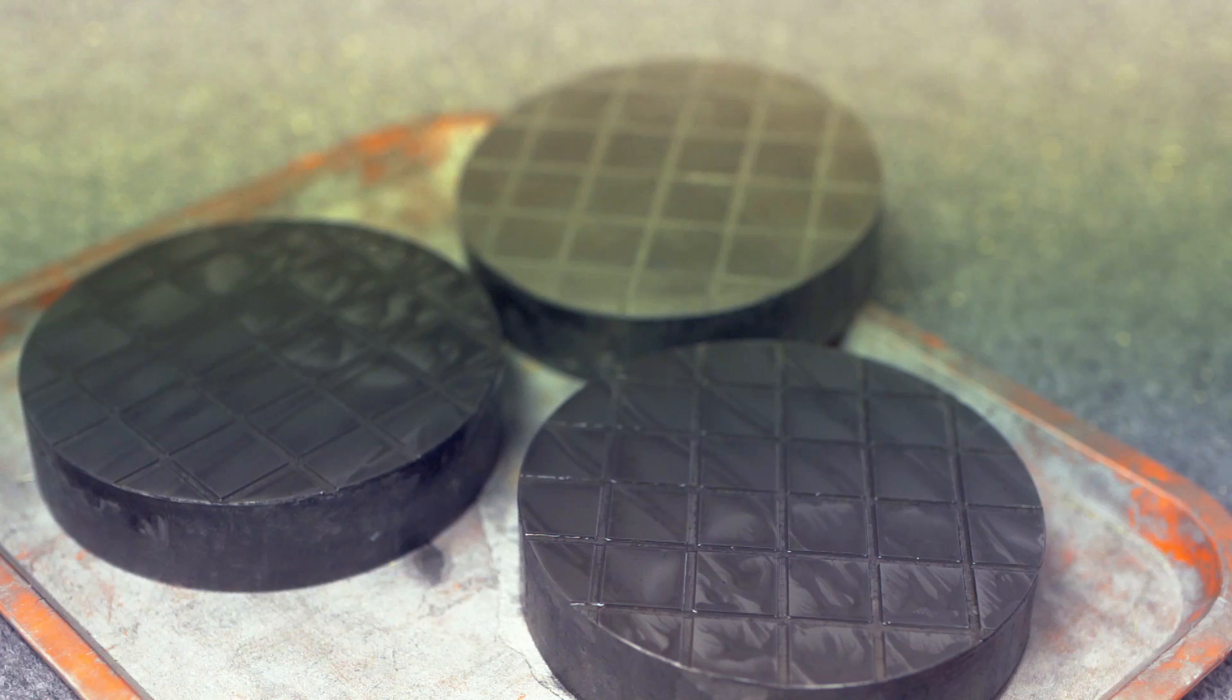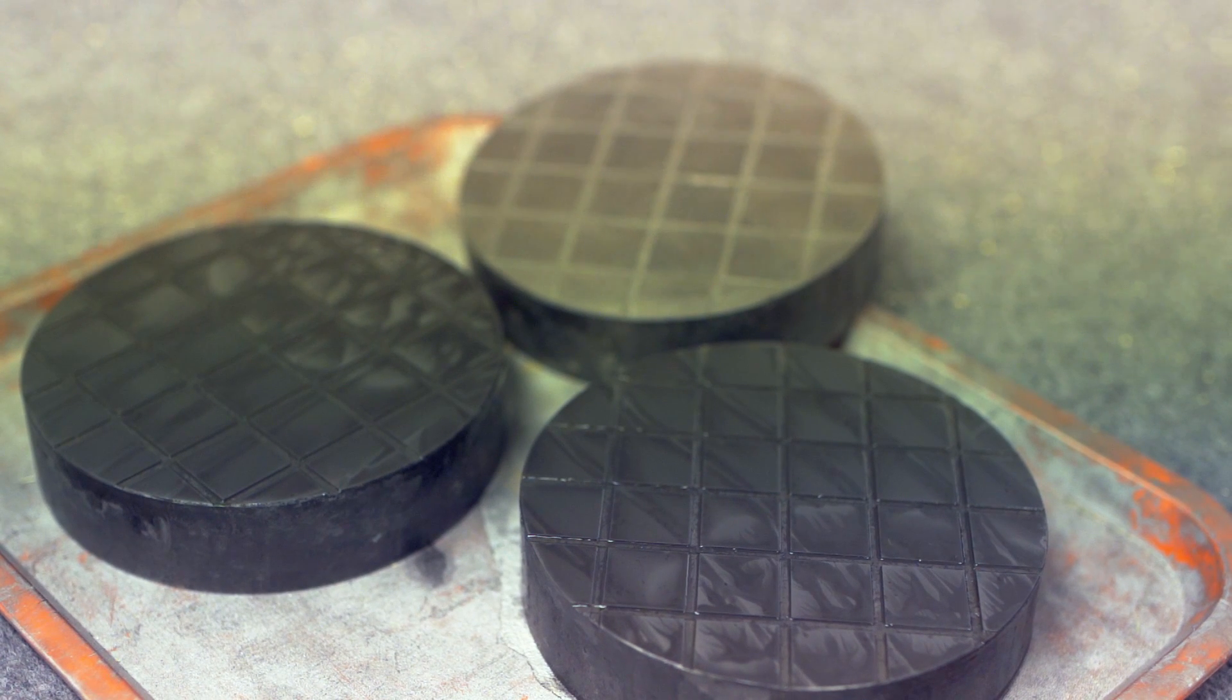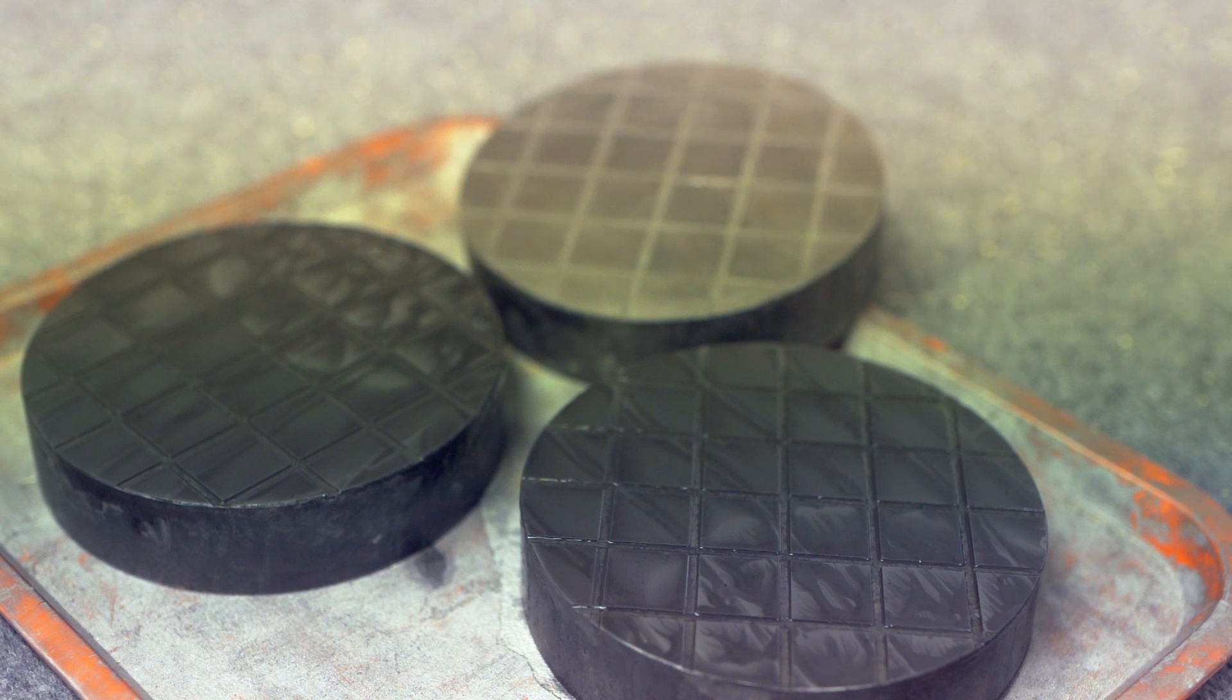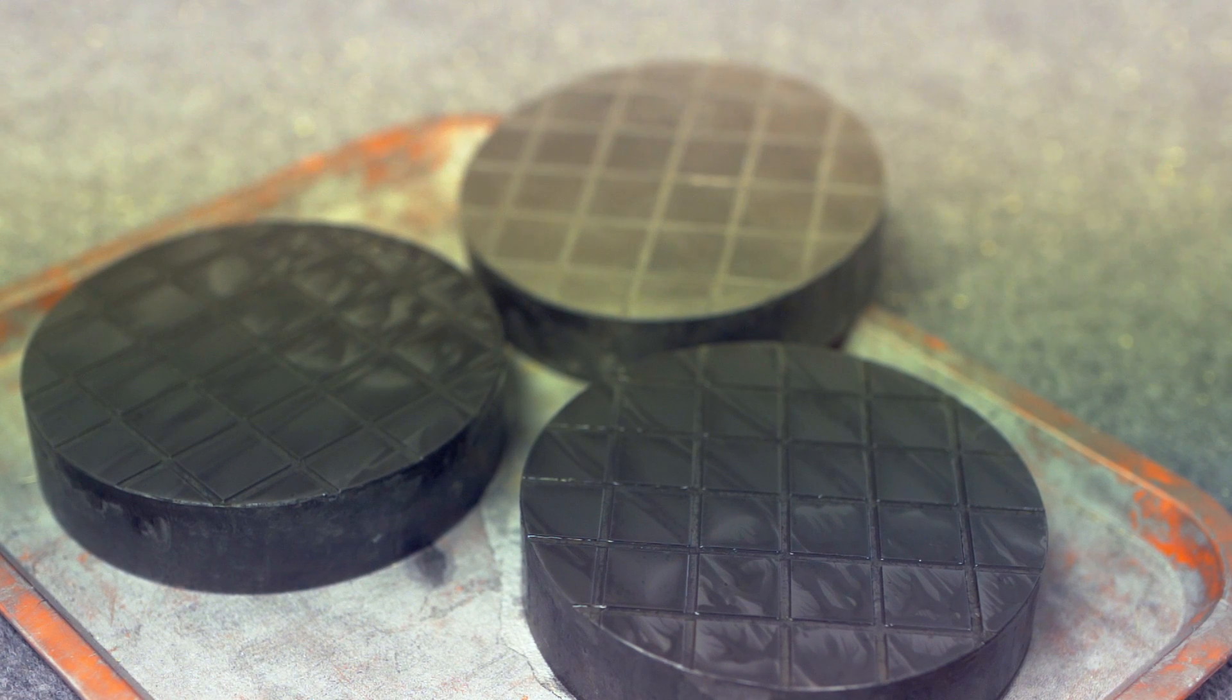So, just what the hell is lapping? What you are looking at are not waffle irons, they're lapping plates. Surfaces of near perfect flatness I made myself after being inspired by Tom Lipton of Ox Tool Co. I cut a chunk of scrap steel into three equally thick plates, and after facing them on a lathe, I started lapping them together.